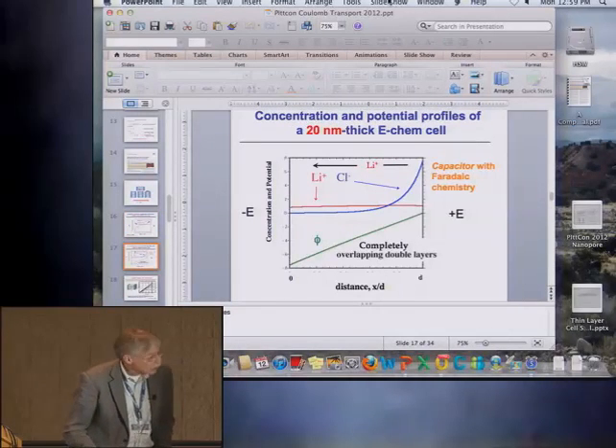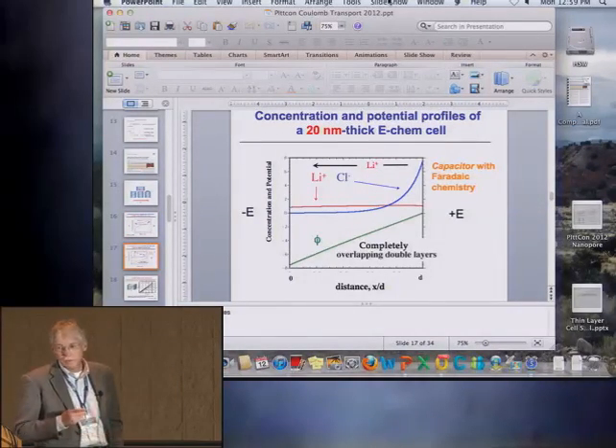If you decrease the thickness of the cell down to 20 nanometers, you get something totally different. First of all, you get a linear potential profile, so the electrical double layers are completely overlapping in this limit. And if you look at the lithium concentration profile, remember lithium's coming out of the right, going to the left, there's no gradient. So at 20 nanometers, the transport of the ions is being completely driven by the charge on the electrode surface, and diffusion doesn't play a significant role. It was a very surprising result, and I still don't know if I've got a really great way to explain it.